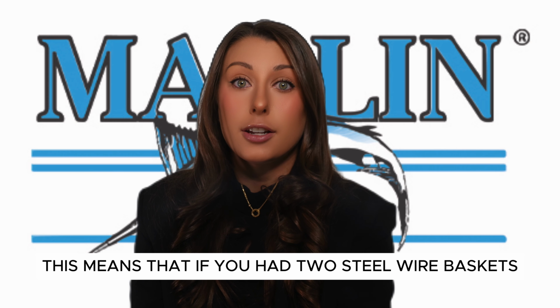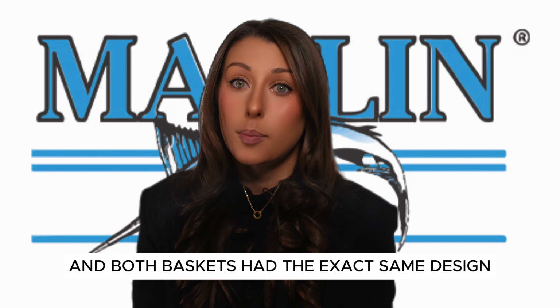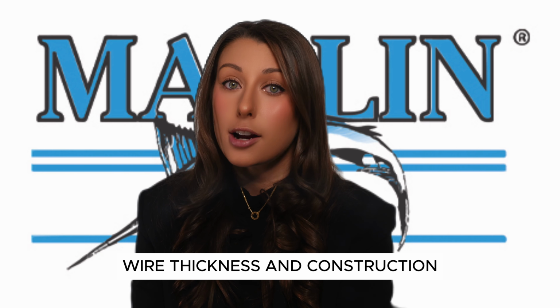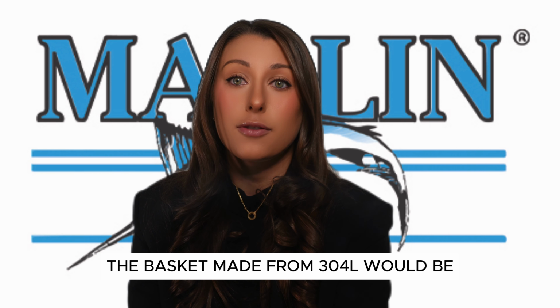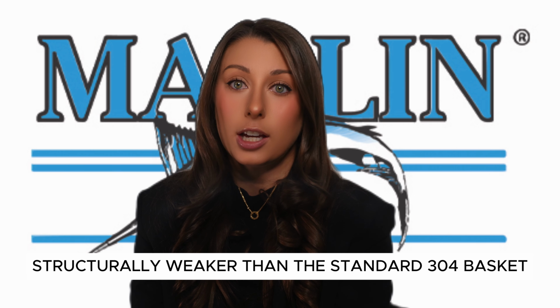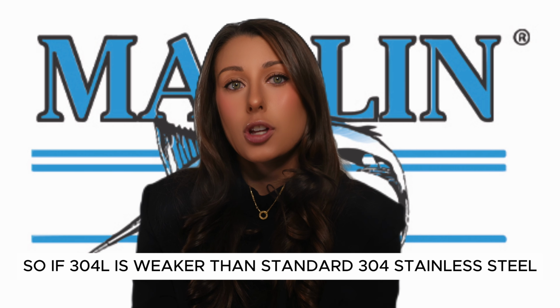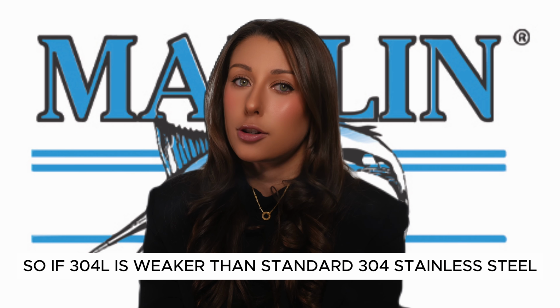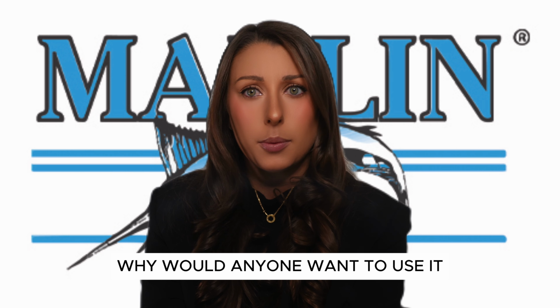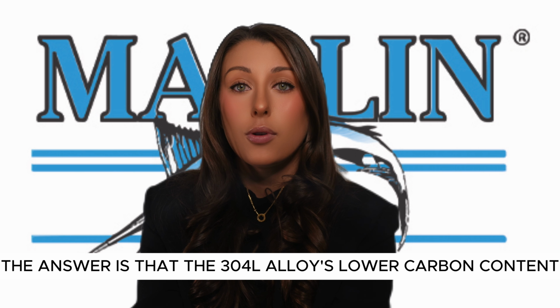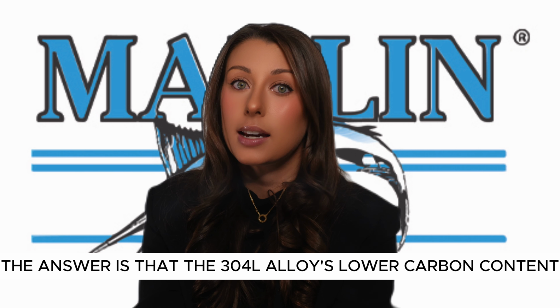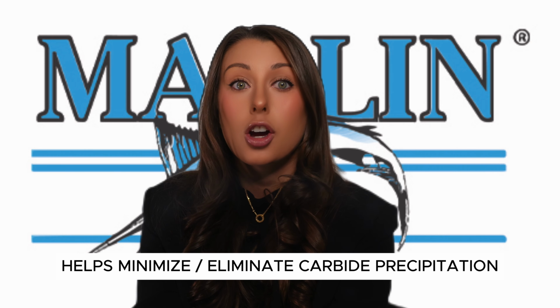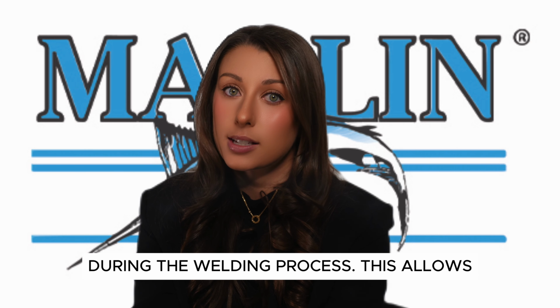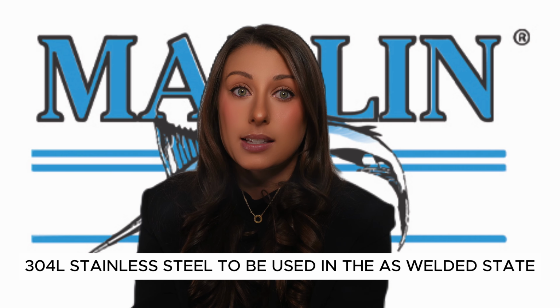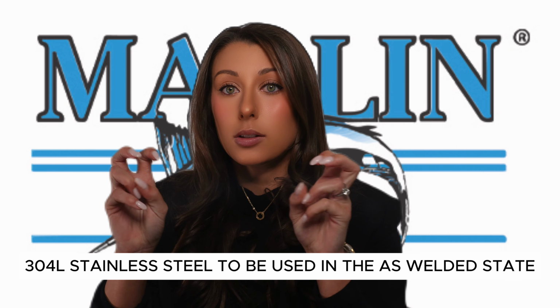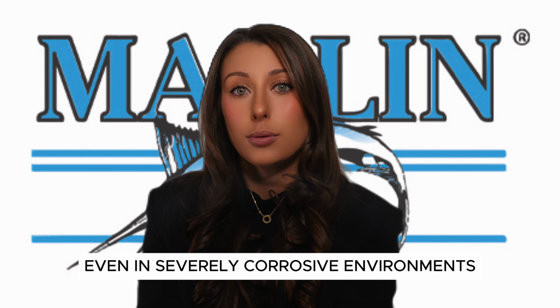This means that if you had two steel wire baskets and both baskets had the exact same design, wire thickness, and construction, the basket made from 304L would be structurally weaker than the standard 304 basket. So if 304L is weaker than standard 304 stainless steel, why would anyone want to use it? The answer is that the 304L alloy's lower carbon content helps minimize or eliminate carbide precipitation during the welding process. This allows 304L stainless steel to be used in the as welded state, even in severely corrosive environments.